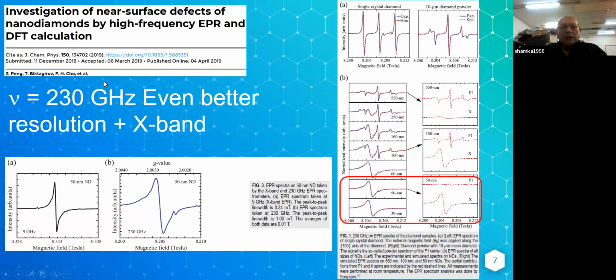Let's go further. Another work was done in 2018, at very high frequency and X-band, 9.4 gigahertz. Again, they got the same results. They have a broad line, which, even with better resolution, is shifted aside. They have the P1 signal, and it changes from a pure P1 signal in large particles to a practically absent P1 signal in 50 nanometer particles and zero P1 signal at 30 nanometer particles.